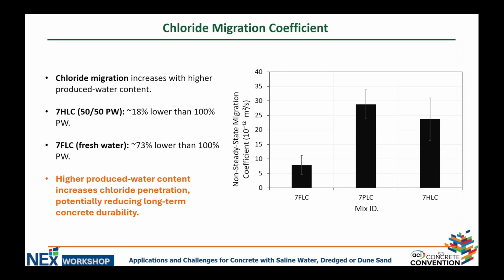of chloride diffusion. But it's not a linear relationship because both the 7P-LC mix and the 7H-LC mix are showing very comparable results. Yes, the 7P-LC shows a kind of higher chloride migration coefficient, but it's not linear, because here it's 100% produced water. In the 7H-LC, it's 50%.